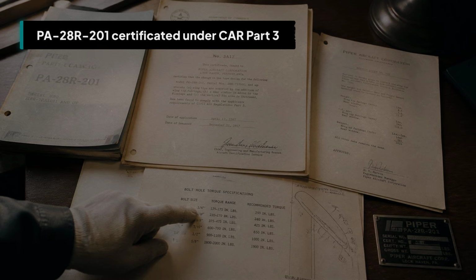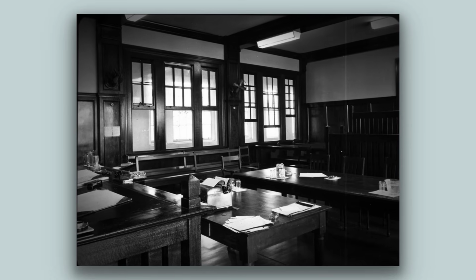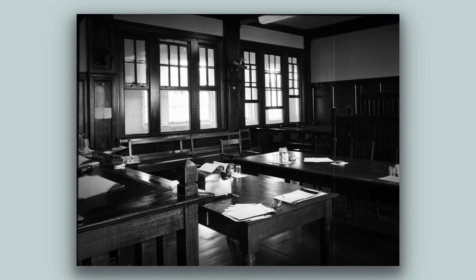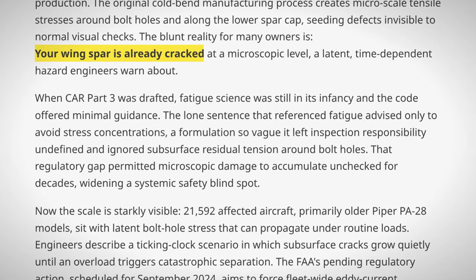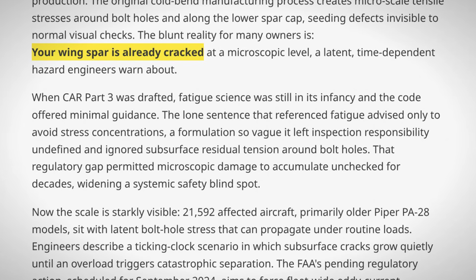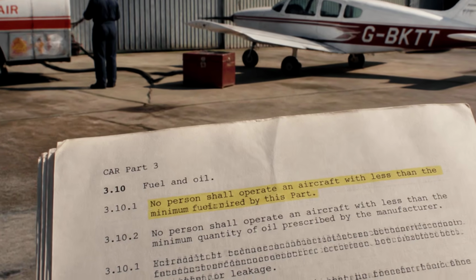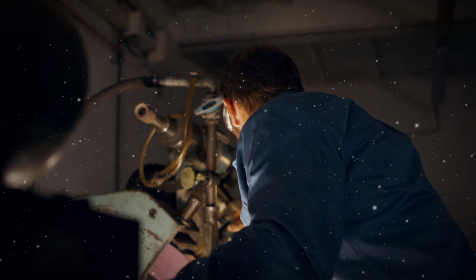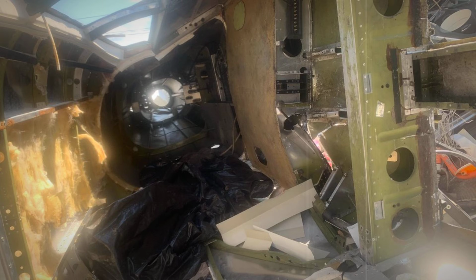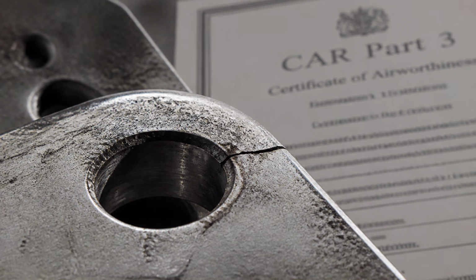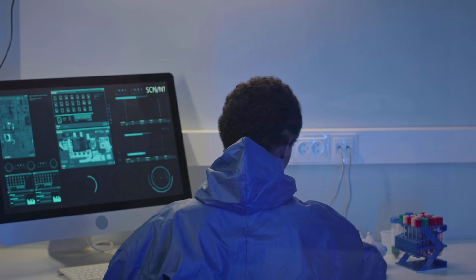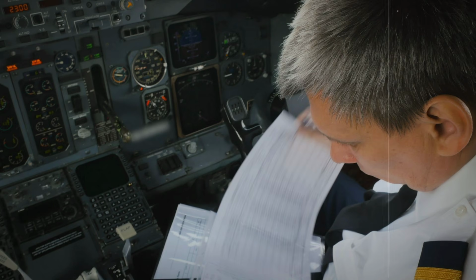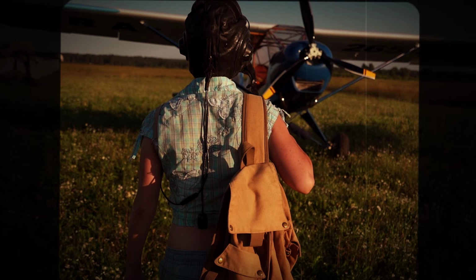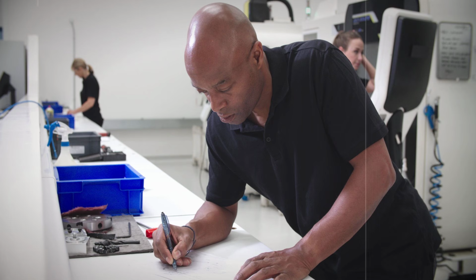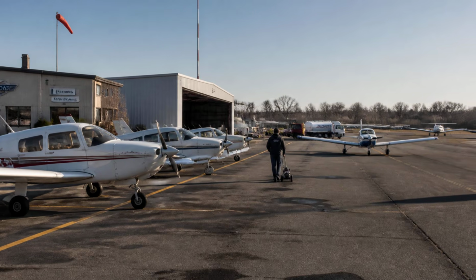Piper type certificated the PA-28R201 under Civil Air Regulations Part 3. That framework predates modern fatigue evaluation requirements entirely. The only fatigue language in CAR3 that touched the spar was a vague line about avoiding stress concentrations. That was the whole standard. Cold bending the spar and then drilling the attach bolt holes through the bend radius satisfies the letter of that requirement. It creates exactly the condition the requirement was intended to prevent. No cyclic load testing was required on the specific spar bolt holes under Part 3 certification. The airplane entered service in the 1960s without a documented fatigue life for that joint. It is still in service now.